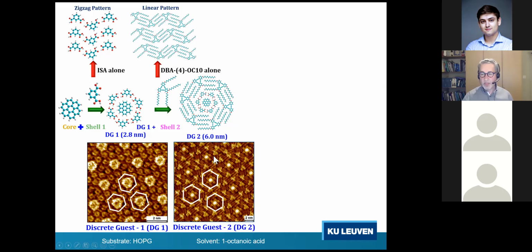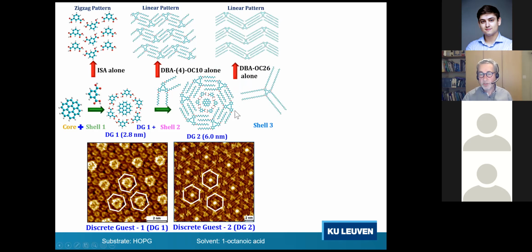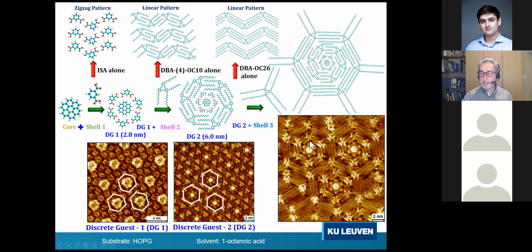Actually, STM is a rather, you could say, simple visualization technique, given that you use appropriate molecular systems. You can clearly see here the bright coronene molecule surrounded by 6 of these shell 1 molecules, surrounded by 6 of these shell 2 molecules. The triangle features over here, these are the triangle cores of these shell 2 molecules, and these long features over here, they are the alkyl chains. So indeed, if we then make a mixture of the coronene, the shell 1, shell 2, and shell 3 molecule, finally we end up with this rather beautiful structure, in which indeed we realize the formation of this kind of multi-component network.